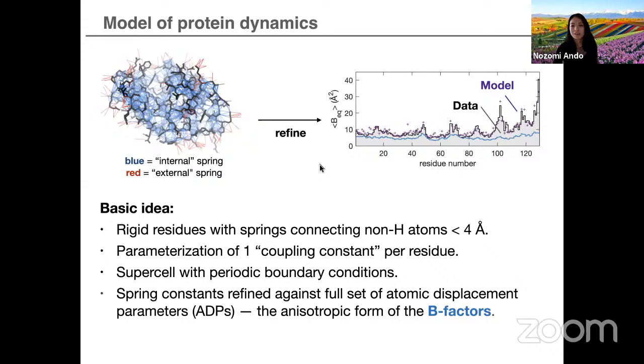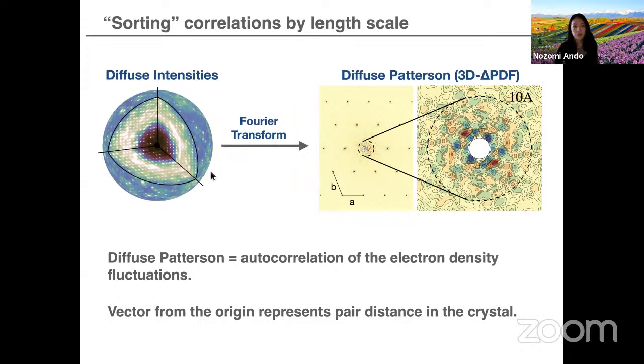Now, to understand how well the model did, we had to plot the data in a different way. Because I already told you that most of the diffuse intensities are accounted for by lattice dynamics, which are the dominant signal, we're now looking for a very small signal. And so it's advantageous to sort the signal by the length scale of the correlations. You can do that by taking the Fourier transform.